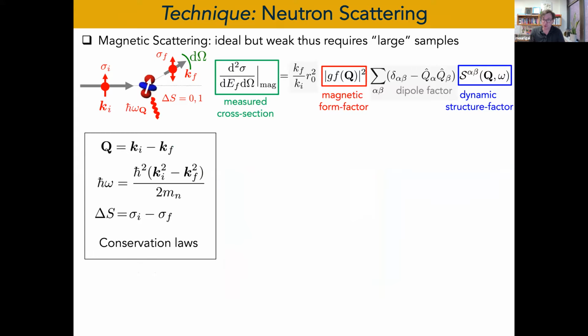I don't want to spend too much time on this. The key feature of neutrons, of course, is that they carry a spin, and through the spin, they can interact with the magnetic moments in the sample. And this scattering process is essentially a conservation of momentum, energy, and spin. We design instruments that have one way or another to capture this kind of conservation law.